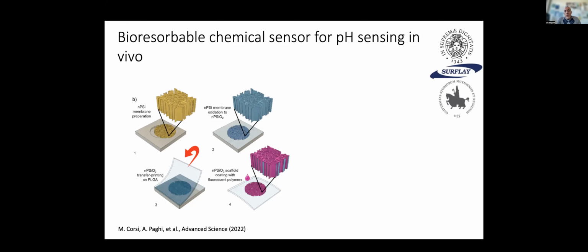Again, in this case, when we go in vivo, we don't want to rely on a label-free approach. It would be difficult to monitor refractive index change in vivo. So in this first proof of concept, we demonstrate fluorescence monitoring of pH in vivo. To do this, we use the same biofunctionalization approach. We use a different polyelectrolyte, and we modify the polyelectrolyte with fluorophores. So basically, the polyelectrolyte we assemble inside the porous silicon scaffold is fluorescent.